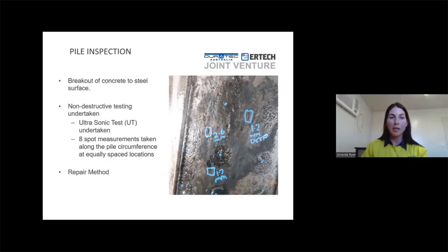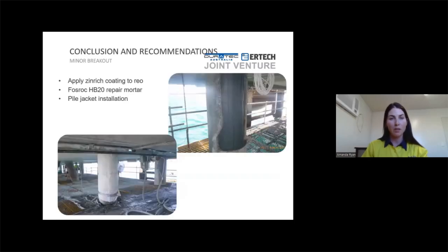So there were 2 repair methods that were proposed depending on the delamination of each pile. For the first repair method, it involved a minor breakout of the delamination area. So we broke back the concrete to the exposed steel. We then coated the steel with a zinc-rich coating. This is what this grey paint looks like here.